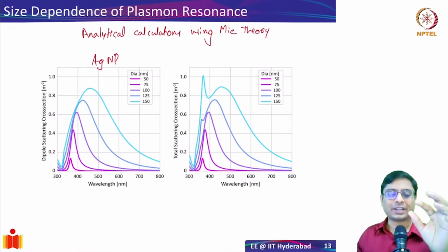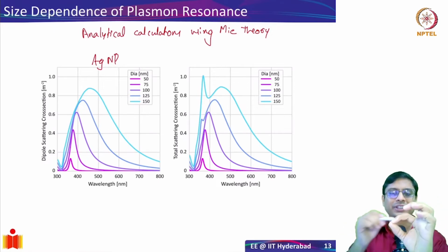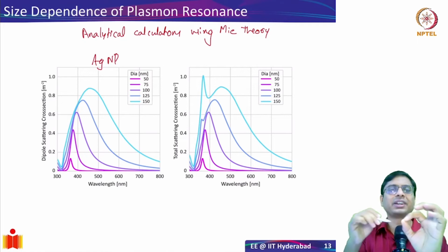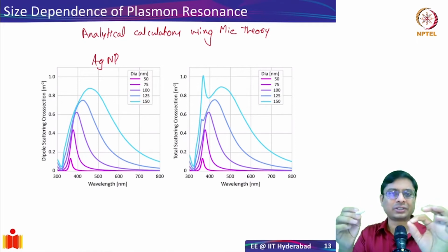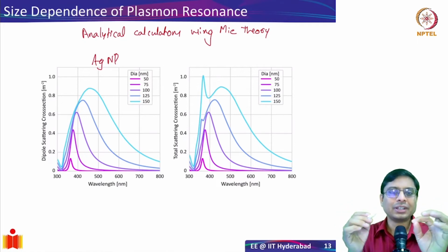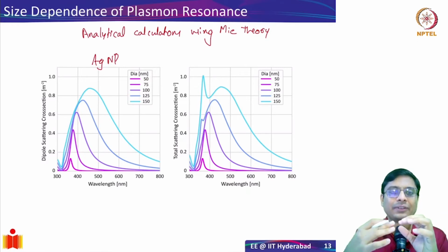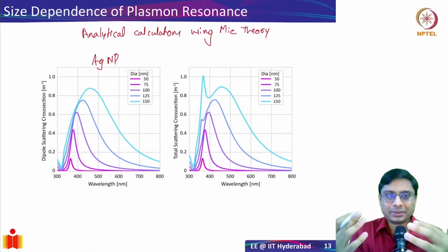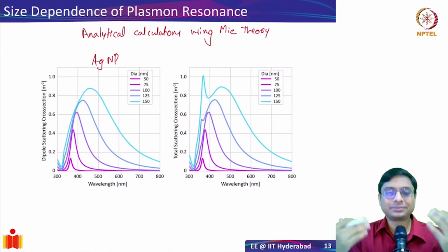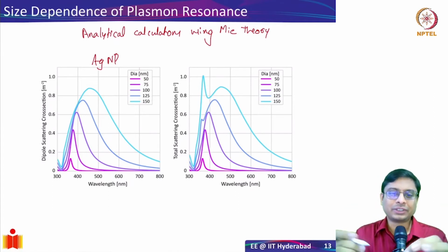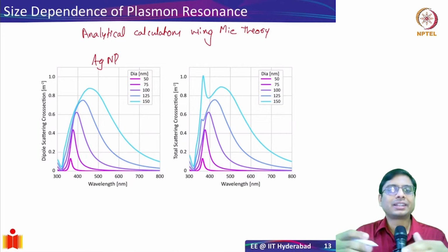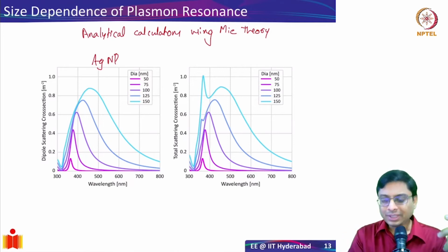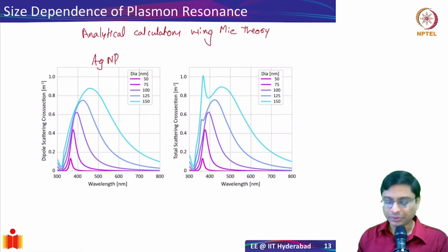So for example, if I take a nanoparticle of this physical size, the cross section is, let's say, pi r squared, where r is the radius of the particle. But because of the resonance, effectively the particle is able to scatter light much better. The scattering cross section is greater than 1. Okay, if I normalize it to the physical geometry, I can get it much higher than 1, and that is what effectively the cross section tells you. So that's a very convenient way of representing it.